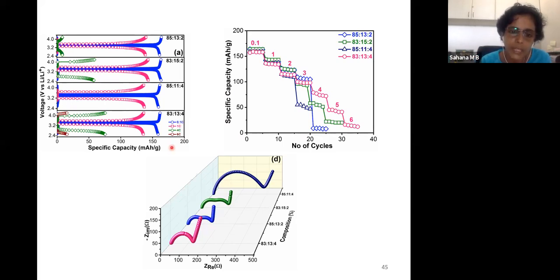So as this number here increases from 0.1, 1, 4 and 6, the current we apply also increases. So now I want you to see here the blue line. The blue line is where the charging and discharging has taken place at 0.1 C, where the current is low. There's not much difference between all the 4 here. All of them give a similar capacity. The x-axis here gives the capacity per gram. So it's around 160 in all the 4 samples.